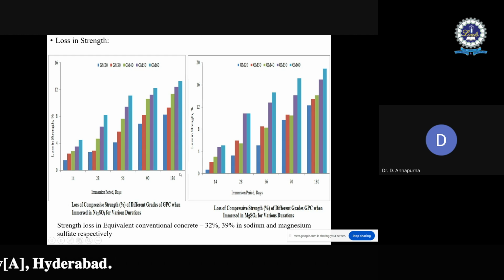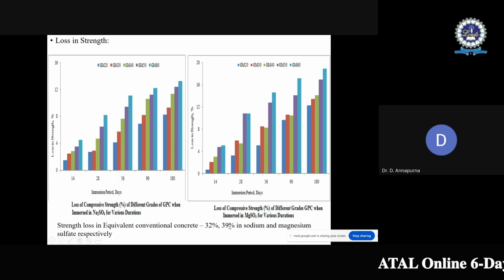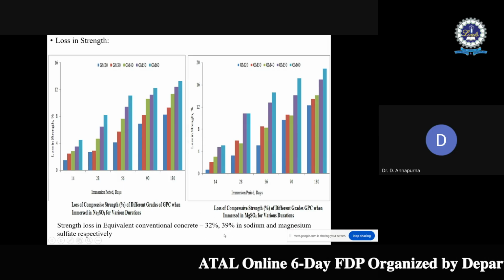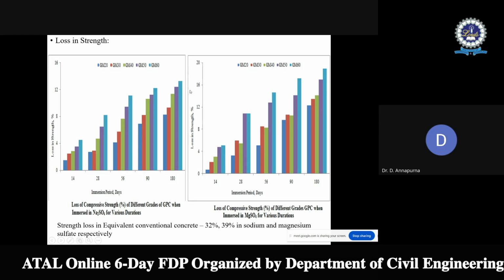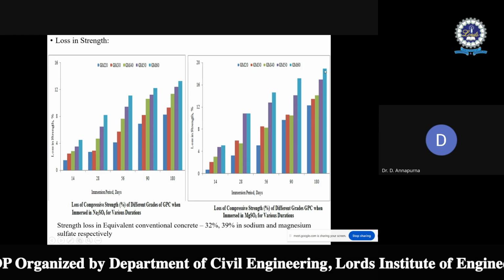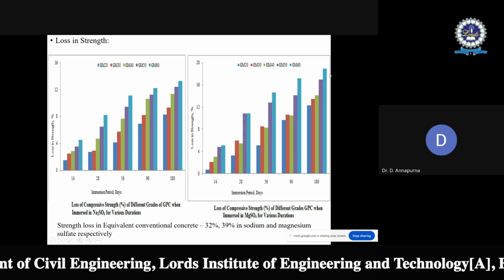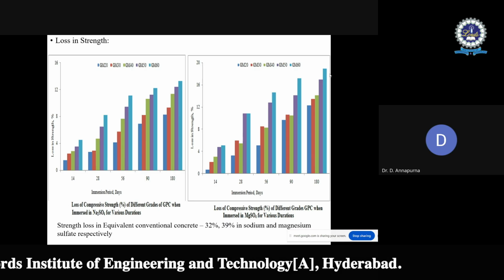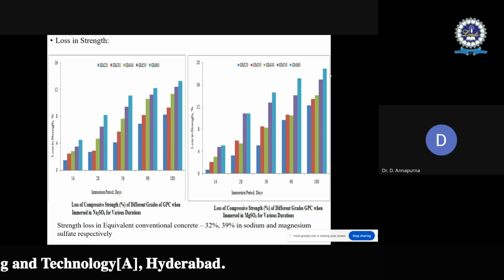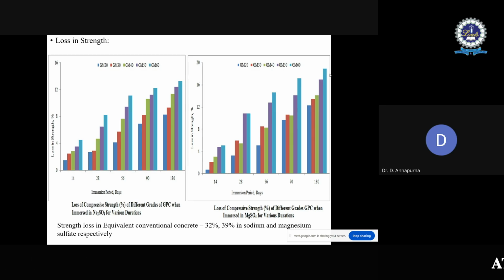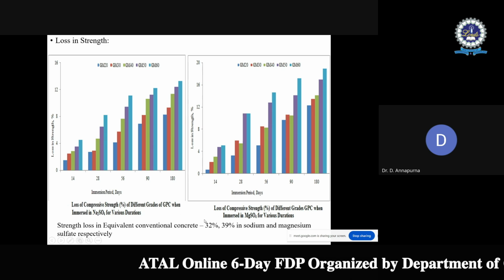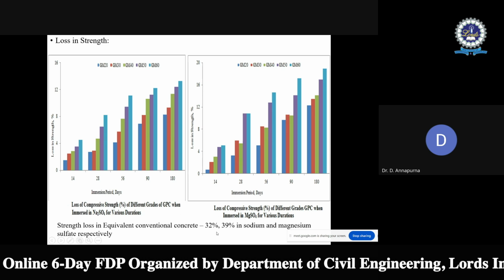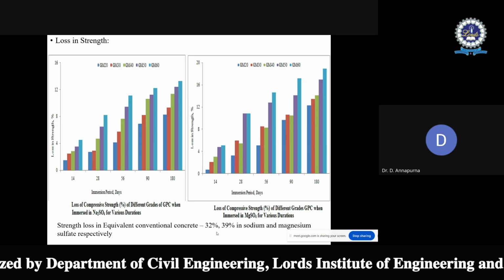But when we look at the conventional concrete, the percentage loss in strength is as high as 32 to 39%, whereas for the geopolymer concrete it is 13% and around 18%. So even though additional calcium in the form of GGBS is added in the geopolymer concrete, and the calcium is reacting with sulfates, its resistance against the sulfate will be very high compared to the conventional concrete. That is what we can conclude through this particular study.